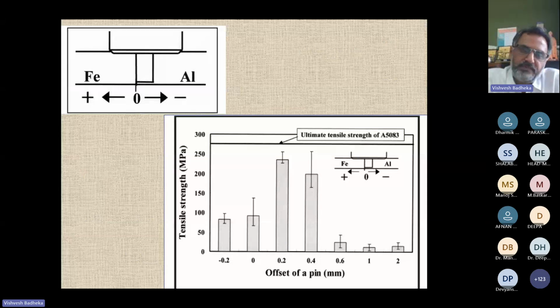Moving further, now you can see here, this is how your properties also get affected when you change the offset value. Here I have taken the example of aluminum and steel. Now you see the positioning of the offset which has been given. This is called the zero position. And if you increase, then the contact with the steel goes up. Zero position may give you close to 100 megapascal strength, right? And as you go further into deeper and deeper to the iron side, 0.2, 0.4, right? You see it has improved from 100 megapascal to around 250 megapascal.